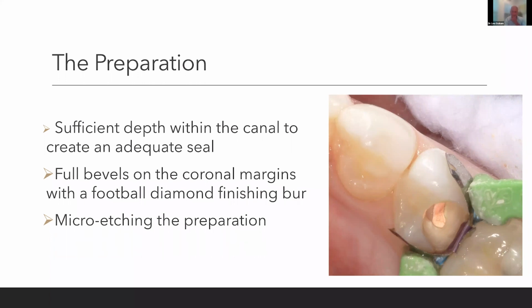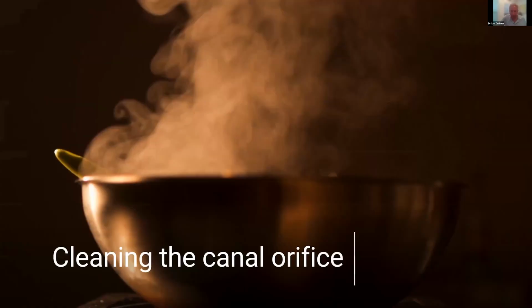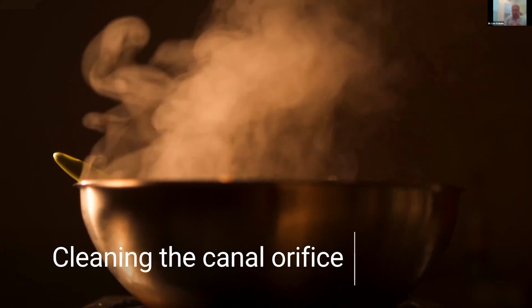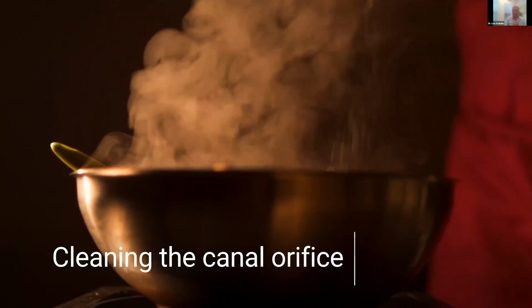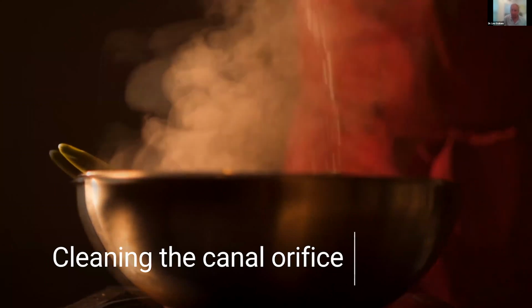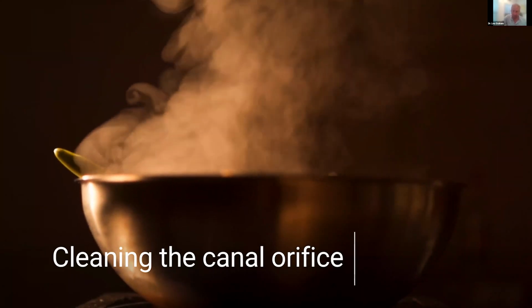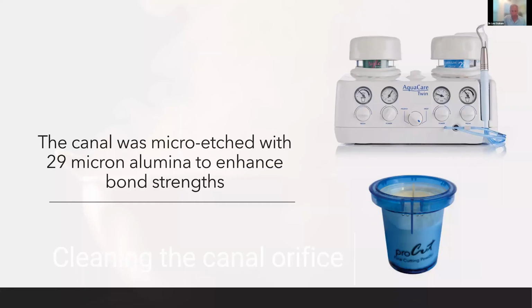The preparation. To begin with, I want to have a sufficient depth within the canal to create an adequate seal. I'm going to bevel with a football finishing burr, usually 50,000 RPMs. You can still go 200,000, but I'm going to bevel the occlusal, and then I'm going to micro etch internally the preparation. And I'm going to tell you, when you're cleaning the canal orifice and your preparation above the canal, this becomes a critical point in long-term bond strength.